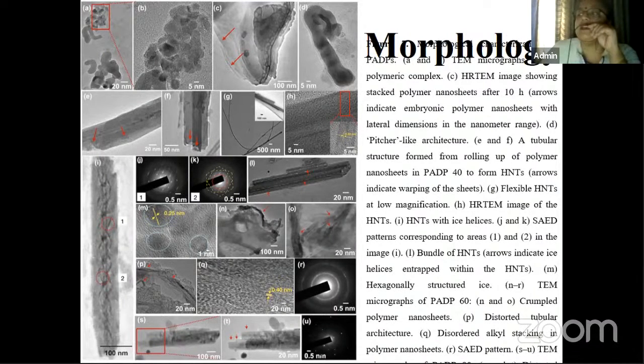internal system has been achieved with the help of TEM analysis, and not only TEM analysis at 24 hours, but we have done TEM analysis at 1 hour, 2 hours, 3 hours. So nanoscale, apart from storage and delivery, may also be used for achieving kinetics of chemical reactions, as is better exemplified by nanopores in zeolites. These are porous materials. Molecules confined in regions with dimensions in the order of molecular size exhibit different physical behaviors compared to large space, having implications in chemical reactions, except for the obvious case when entropic effects are important. Reactions involving larger activation volume change are also affected by confinement in nano compartments.